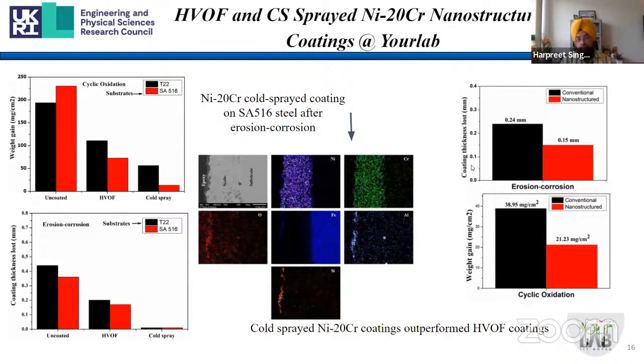We then wanted to develop nanostructure coatings. In fact, one of my colleagues was extracting this nickel and chromium from some of the waste plants, these pickling plants in a nearby industrial valley town. So our dream was that we could extract those nanoparticles of nickel and chromium from that sludge and then form them as a coating. But of course, we could avail some powders, and we developed some nanoparticles through our chemical routes as well.